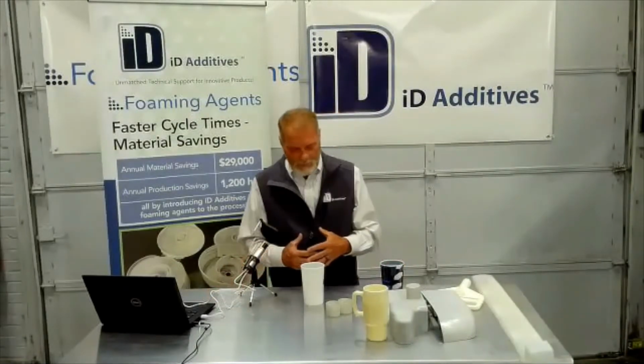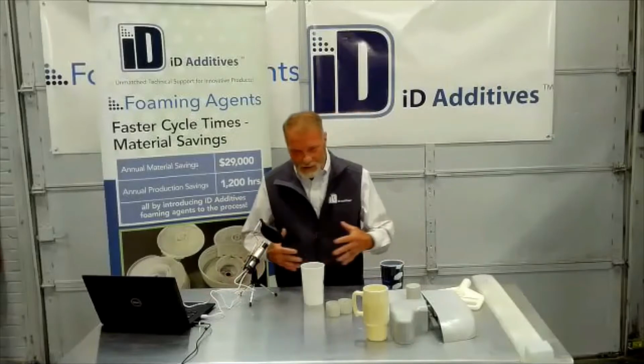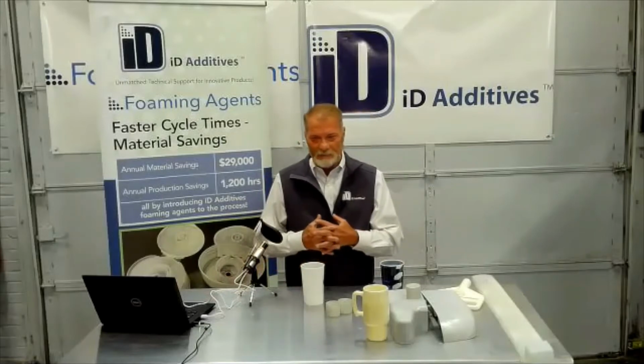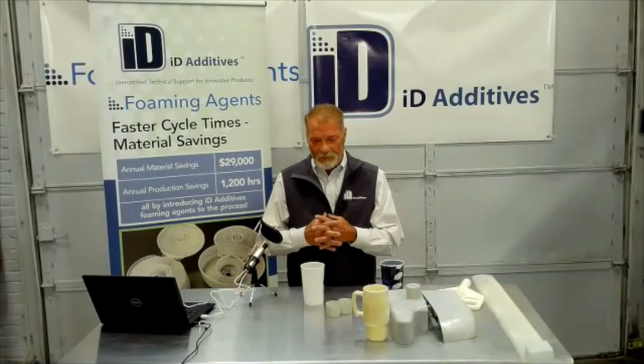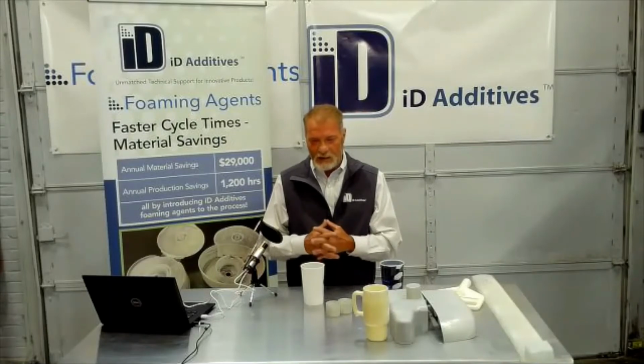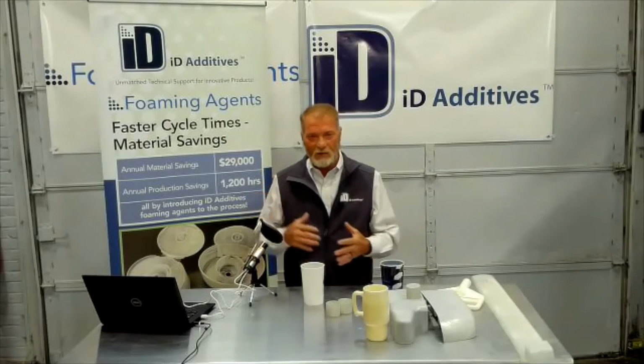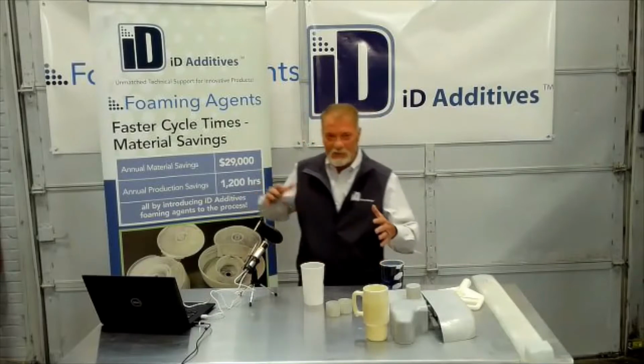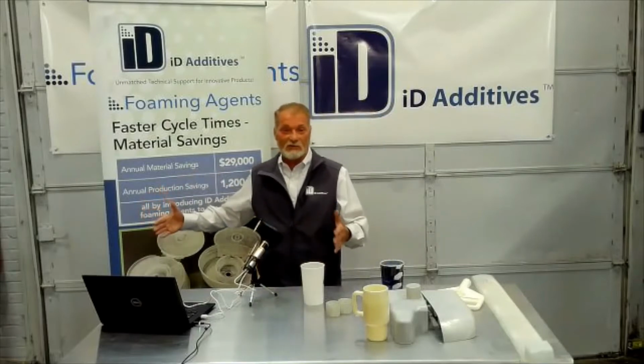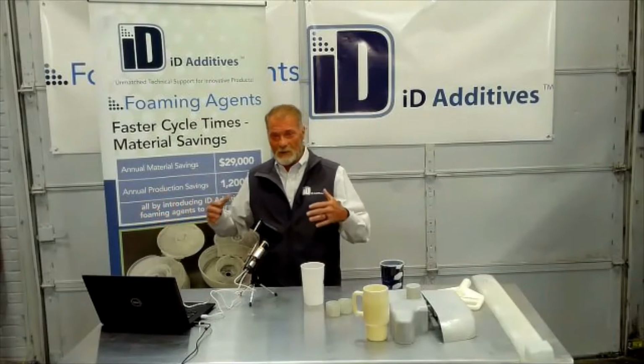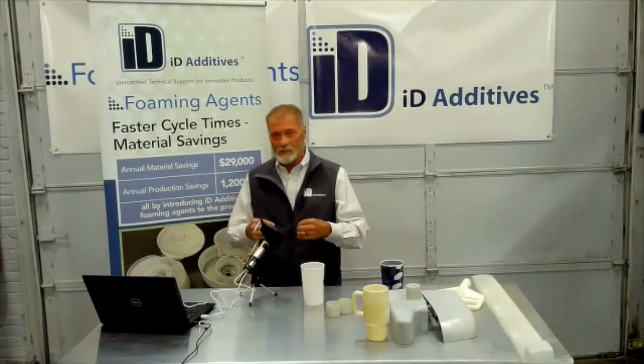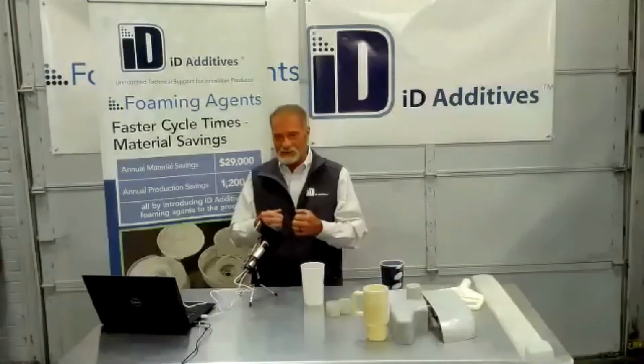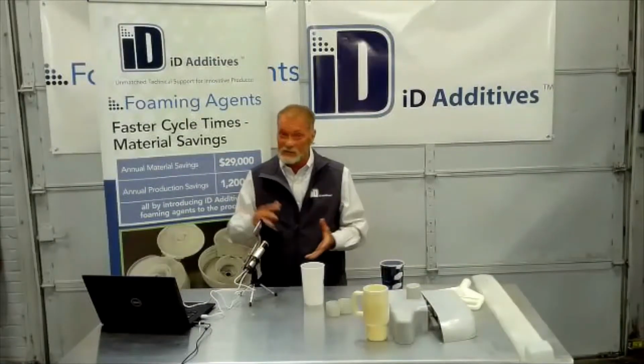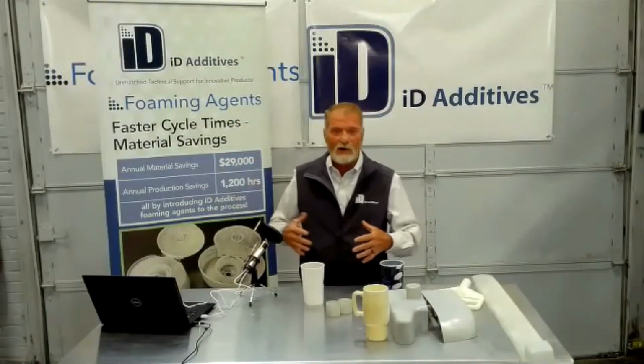And now that we're getting into extrusion here, you want to add screen pack. You want to get that head pressure up. What that does is it creates pressure on the material in the screw. So remember, foam, if it's not under pressure, it's a low pressure application. It sees a low pressure, it starts to expand. But if it's under pressure, it doesn't want to expand.